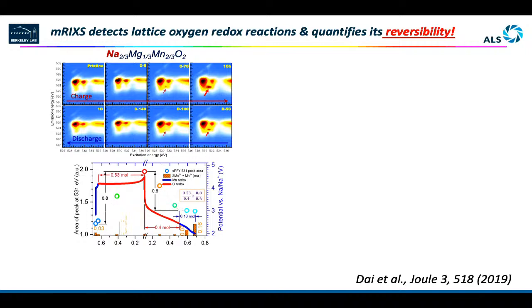If you count the total intensity, you just integrate the intensity of the feature, and those are the dots plotted on here. If we calculate the ratio of this compared with the estimated oxygen redox, there's a perfect match. Because we can see the transition metal redox, we can quantify. So we just get that deducted and we can match the capacity. The ratio shows an excellent agreement.